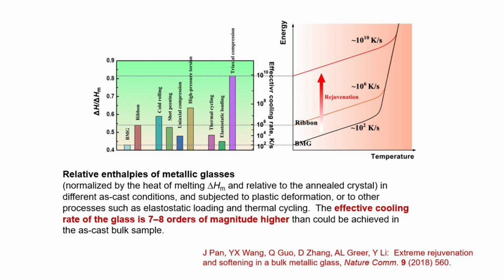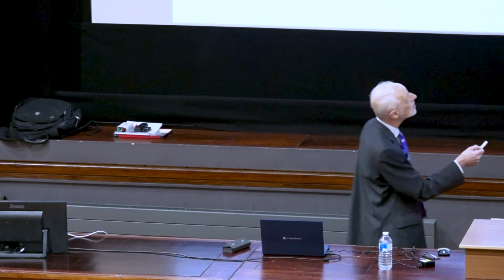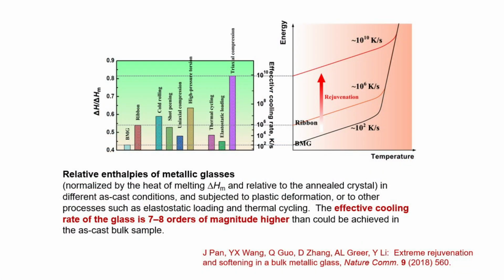This is a little schematic of cooling the liquid into a glass and saying, well, if you cool it faster, you can get a glass with a higher energy. So maybe you could use these processes to mimic faster cooling. And it turns out you can. And if you put it to extremes, you can make the glass think that it was cooled by quenching at 10 to the 10 Kelvin per second, when it was actually cooled at 10 to the 2 Kelvin per second, in terms of modifying its structure after it was formed.